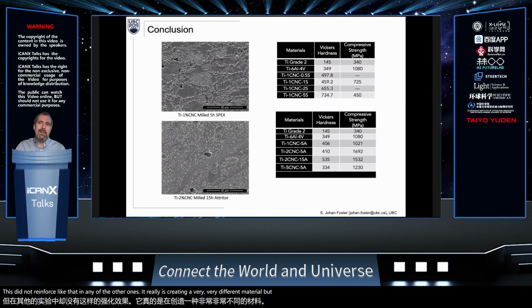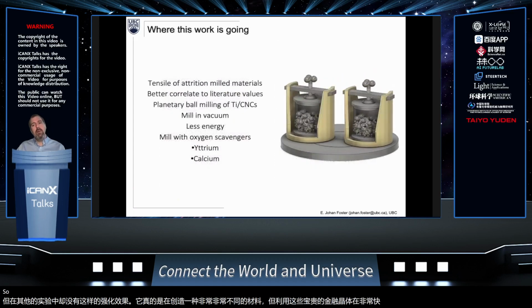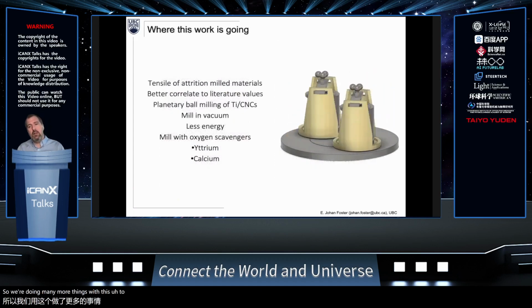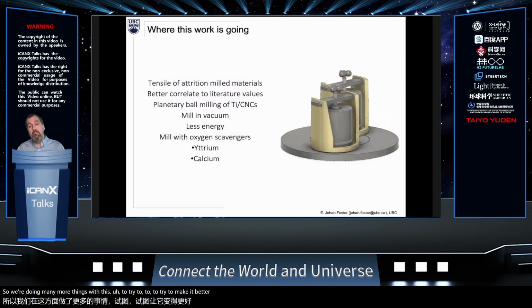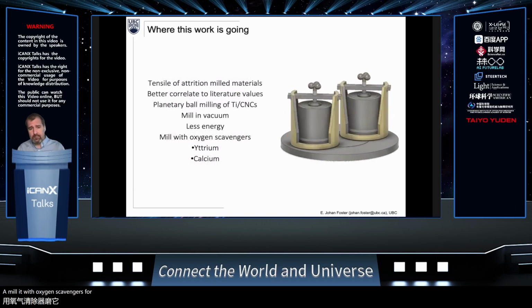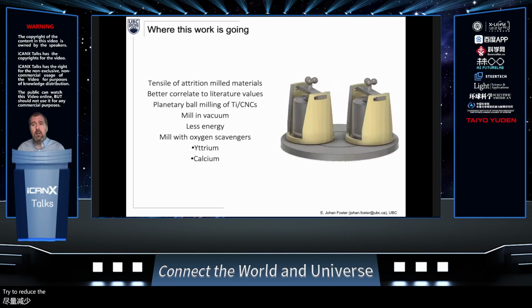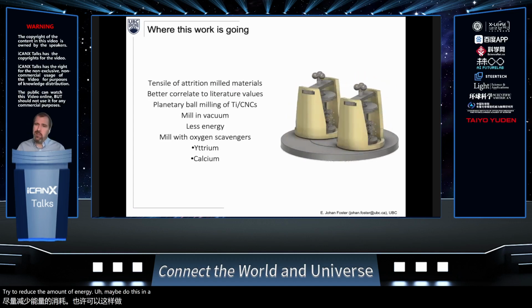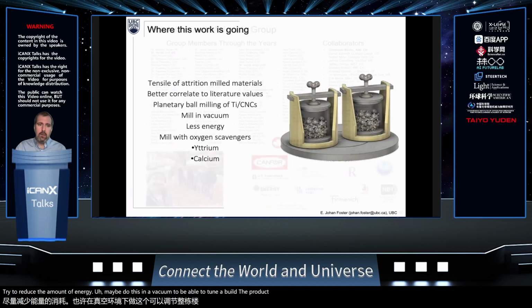We think this was very serendipitous in that this did not reinforce like in any of the other ones. It really is creating a very different material, but utilizing those cellulose nanocrystals in a very unique way. So we're doing many more things with this to try to make it better. Mill it with oxygen scavengers, for example. Try to reduce the amount of energy. Maybe do this in a vacuum to be able to tune the properties. Okay. So with that, I'll wrap up.